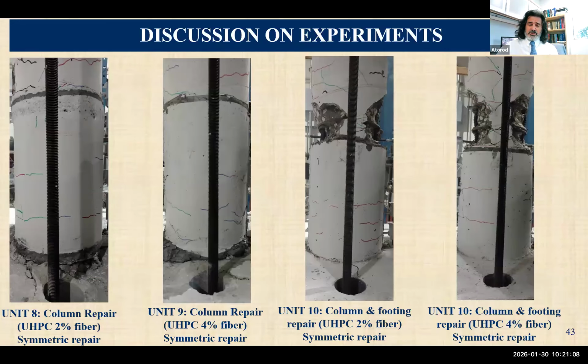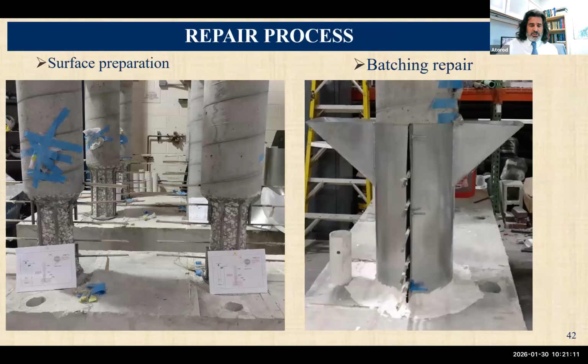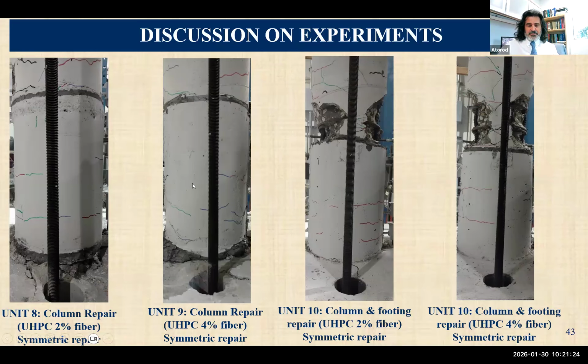One thing that we have found out is that, here, for example, you can see some specimens where we intentionally didn't cast the bottom portion, representing some damage, and then we wrapped it with UHPC. One lesson that we have learned is that any place that you wrap the column with UHPC, if you do it correctly, you shift the damage. UHPC is so strong that you do get some hairline cracks, but you shift the damage to somewhere else, above or below.